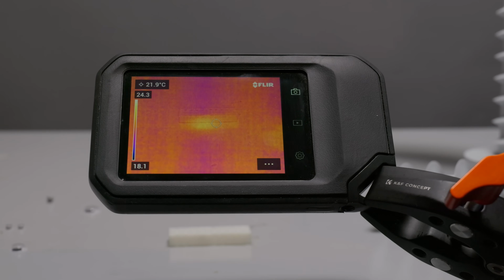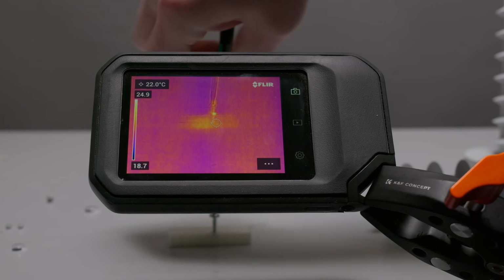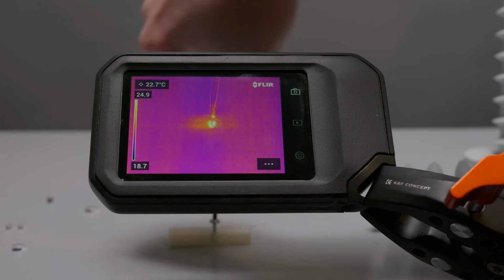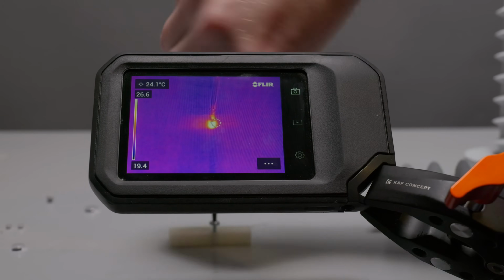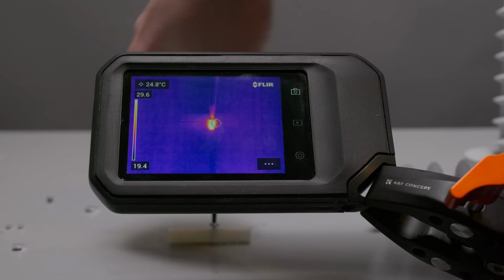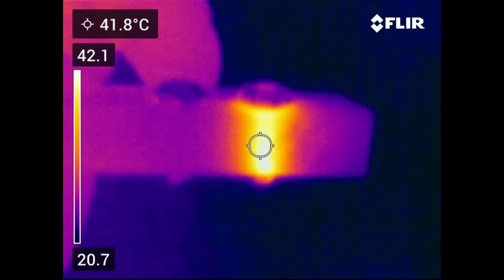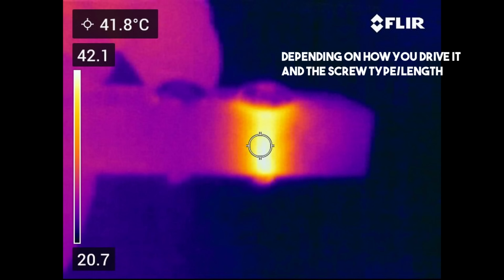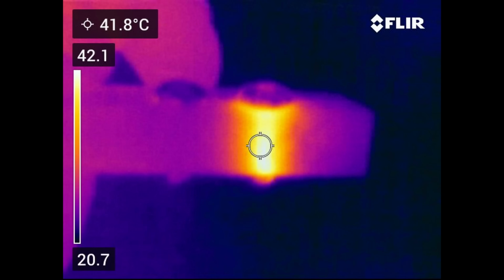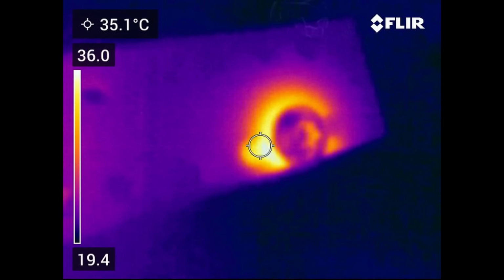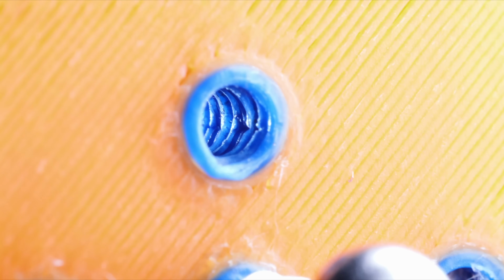Watch what happens on the thermal camera when I drive one of these screws into a pilot hole. The surface temperature you're seeing peaks at about 40 degrees C, give or take, but that's conducted through the plastic, so the actual temperature at the cutting tip is higher. Work through the maths, I don't really want to personally, but you will get to potentially instantaneous temperatures of around 80 degrees C or above, which for PLA is above the glass transition temperature, and that's the same for quite a lot of plastics.